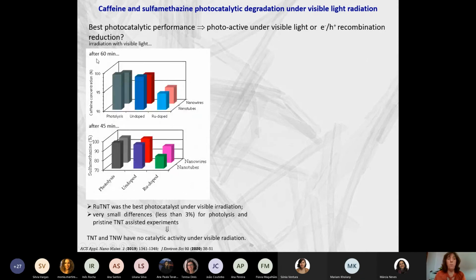But as you remember, I told you that we are interested in try to shift the absorption edge of these materials to the visible, and we are also interested in try to see if we reduce the recombination of the charged carriers. For that, we decided to repeat these experiments under visible light for sulfametazine and caffeine. And in fact, when we have the ruthenium doped samples, we have better performance than the ones that we have for the pristine materials. This is under visible light.